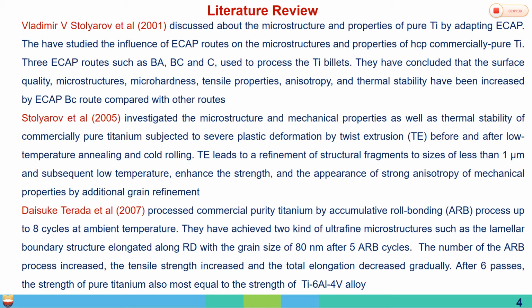Another researcher investigated the microstructure and mechanical properties of commercial pure titanium processed by the twist extrusion technique. They achieved good strength by reducing the grain size to less than 1 micrometer, which enhances the strength of the material. Another researcher worked on pure titanium with accumulative roll bonding techniques. They achieved an 80 nanometer grain size after 5 ARB cycles. After 6 passes, the strength of the pure titanium is almost equal to the strength of Ti-6Al-4V.